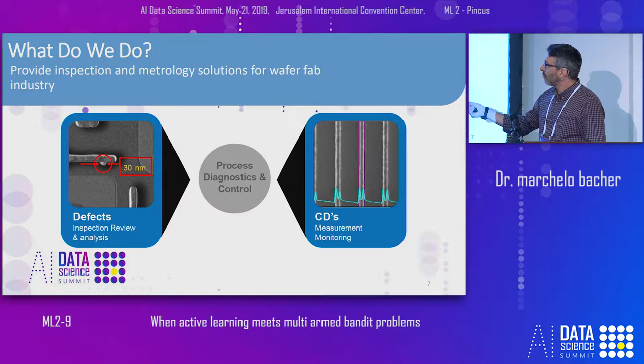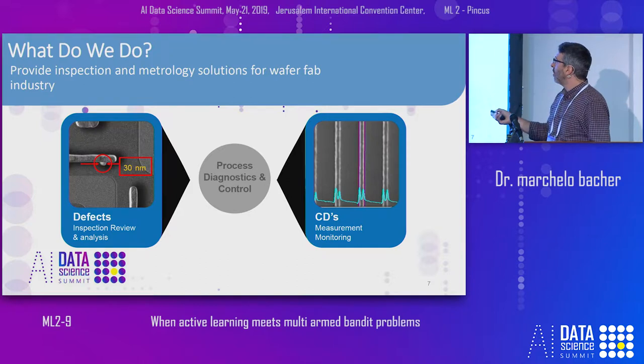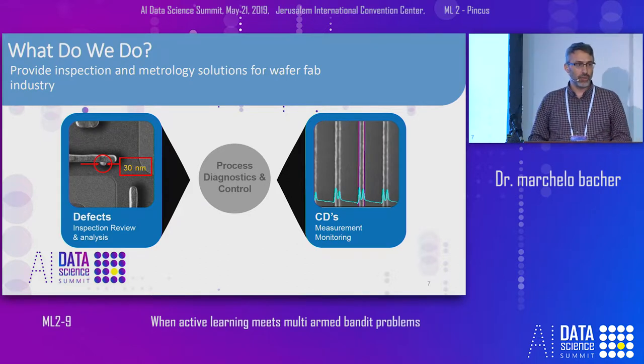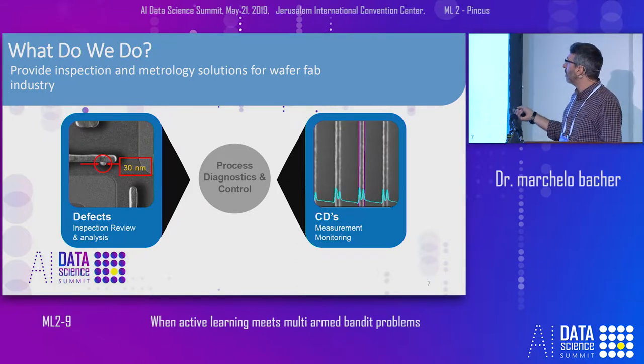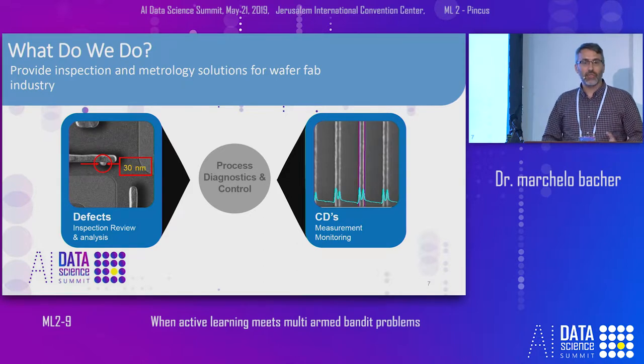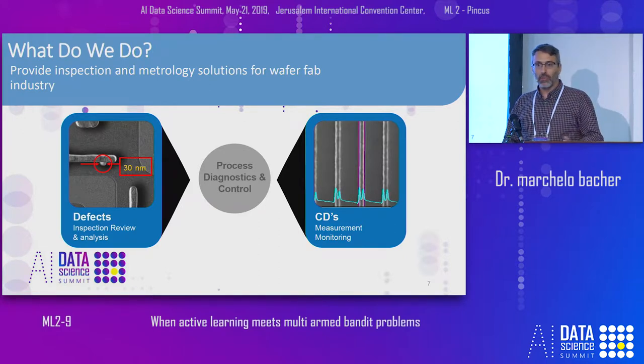For example, on the left side, we see a 30 nanometer defect that we have to spot and also categorize what kind of defect it is during the process. On the right side, we also measure some characteristics of the sub-structure of transistors — in this case, the path that is measured, which can cause energy loss and malfunction of the chips. So we also have to measure that kind of characteristic and inform the customer where the problem might be.